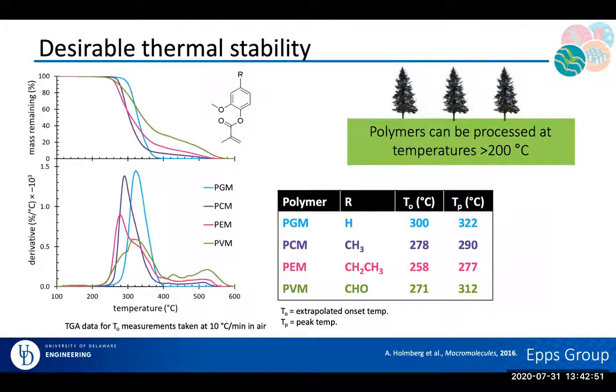Now that's nice. Do we have the thermal stability? And the answer is yes. I won't focus too much on the TGA, or thermogravimetric analysis, data here. I will just mention that our onsets of degradation are all well above 200 degrees Celsius. I should also point out that we do these experiments in air as opposed to nitrogen. One of the reasons we do that is so that we can better mimic the processing conditions that you might see in a commercial production type setting, which is in air as opposed to an inert environment.